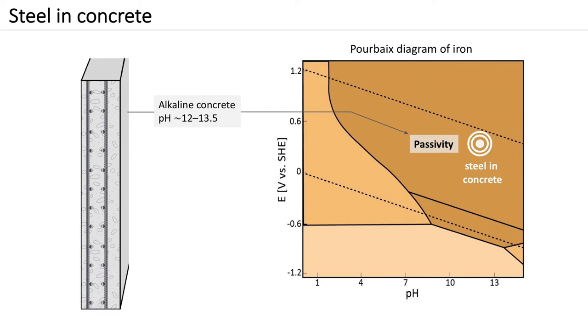Nevertheless, corrosion of the reinforcing steel can be caused by different mechanisms, namely by carbonation of the concrete and by local breakdown of the passive film due to the presence of chlorides.